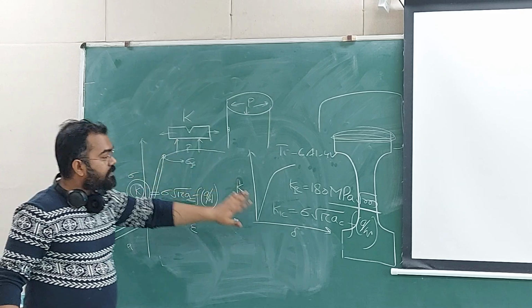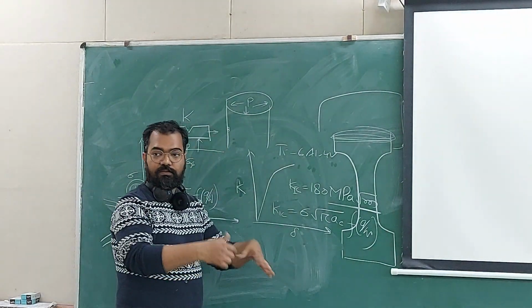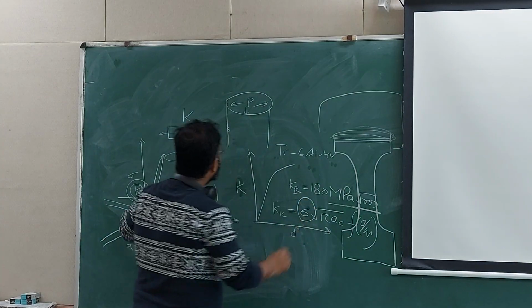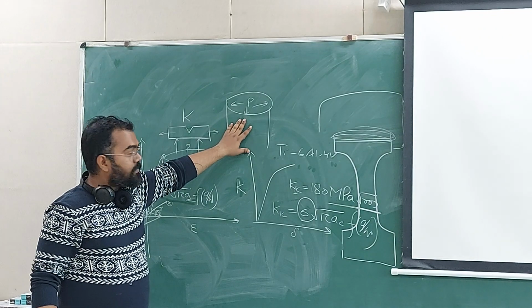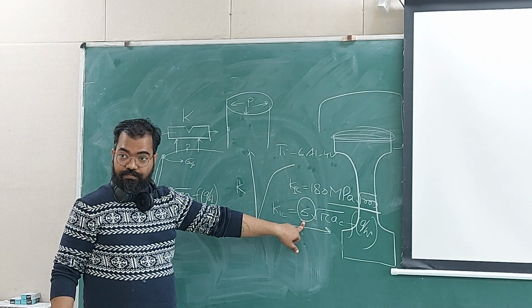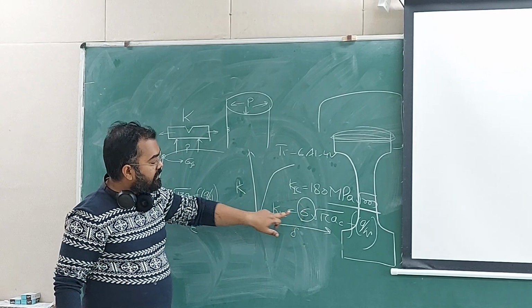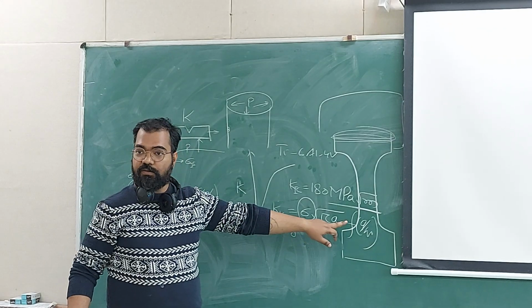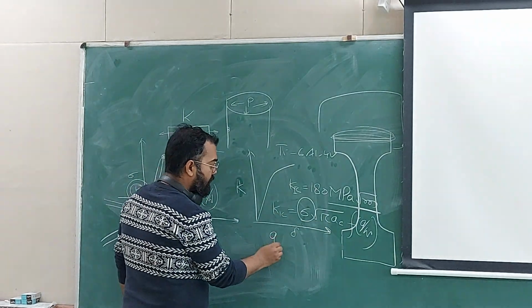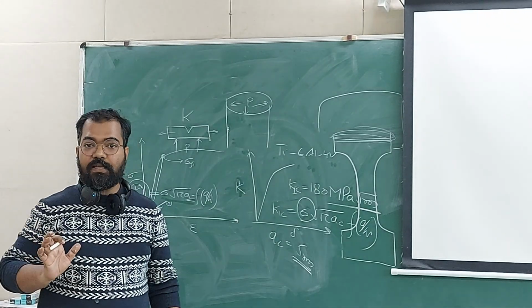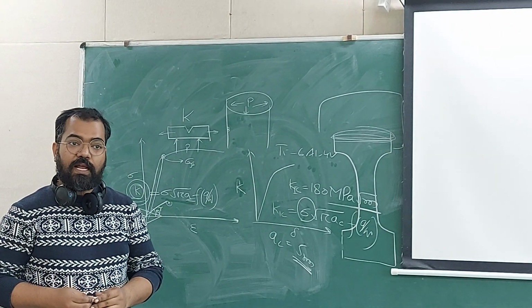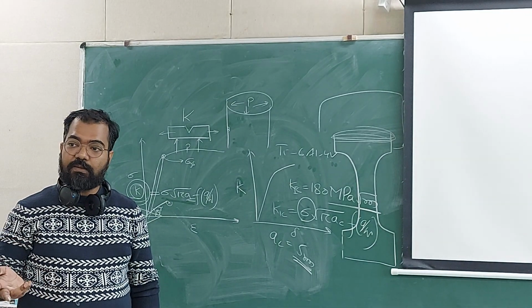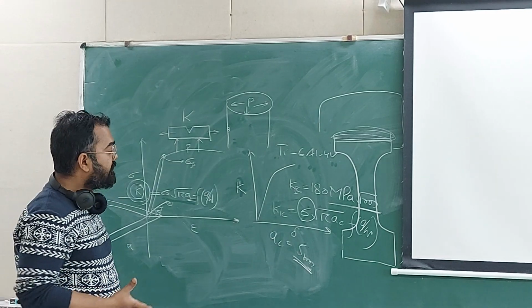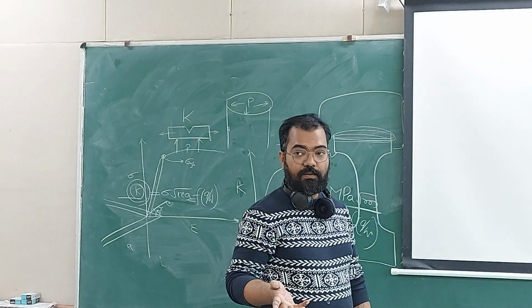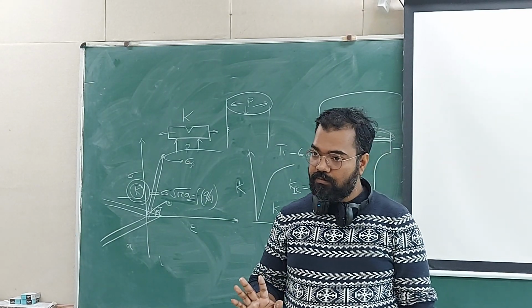From this I can calculate: f of a by w I know for mode 1, and then I should know how much hoop stress is there in that pressure vessel. From that I know my operational stress condition. I plug that in, I know this value, I know that value, pi everyone knows, so I can calculate a_c. Suppose a_c comes out to be 5 millimeter. Then no crack in my system should be larger than 5 millimeter. Then I do ultrasonic testing and see that the maximum crack I am getting is 3 millimeter. If it is 6 millimeter or 5.5 millimeter, I will not take that plate or sheet, I will reject it. Understood the importance of K1c?